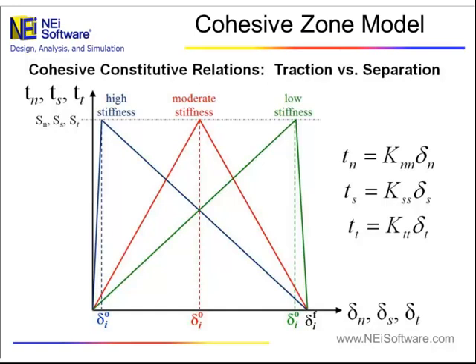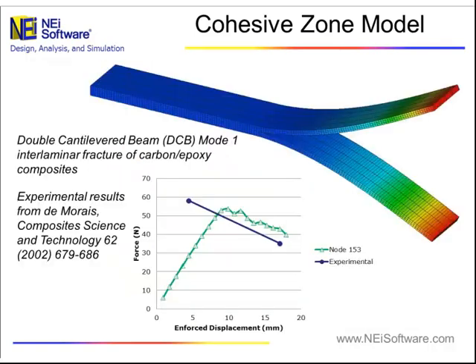It's basically a classic triangular traction-separation law. For adhesives, the local failures are governed by this traction-separation curve. The bottom axis is displacements and the top is the interfacial stresses. At these local regions, the stresses will build up as it reaches a peak interfacial strength allowable. Once it hits that, the adhesive in that region will start to soften and continue to soften until it reaches a final interfacial allowable displacement. At that point, the bond completely fails in that location and the structure is able to pull apart.